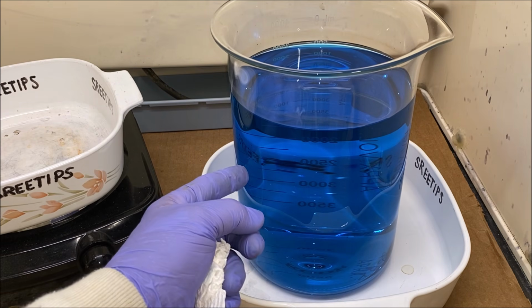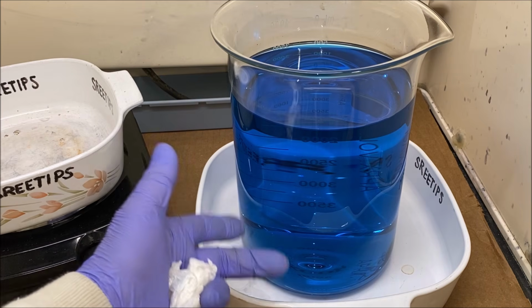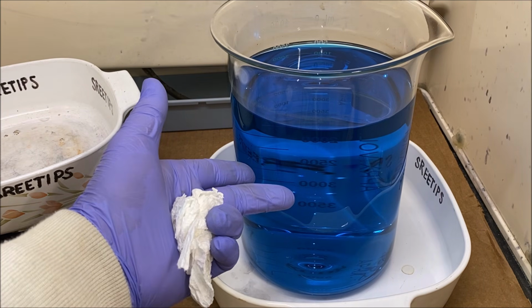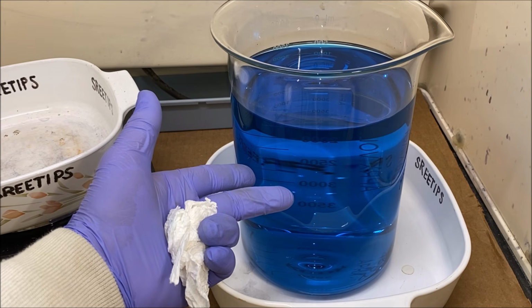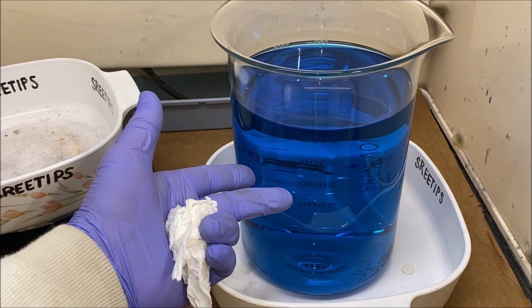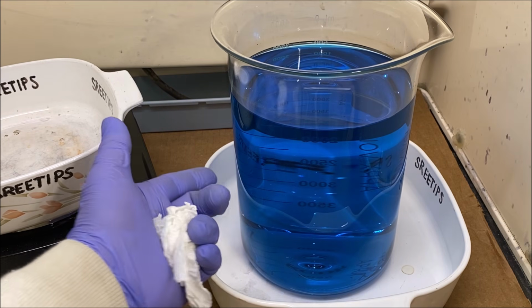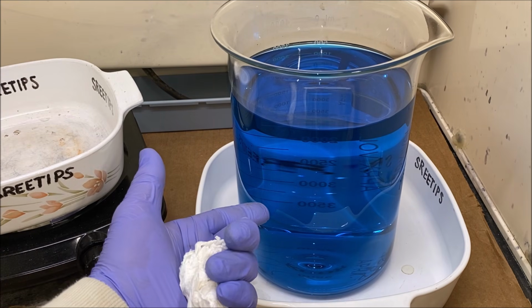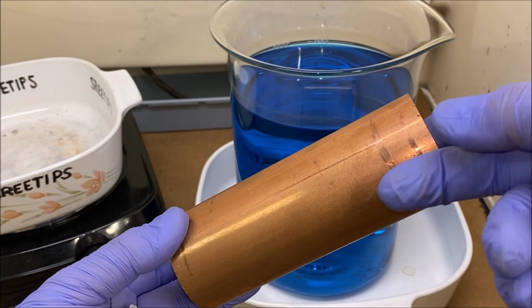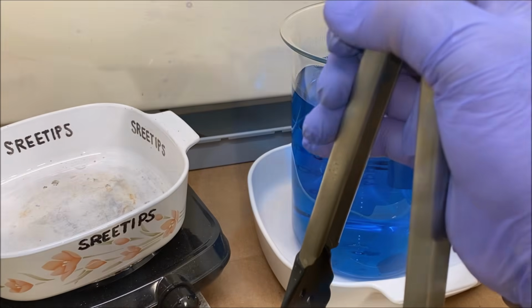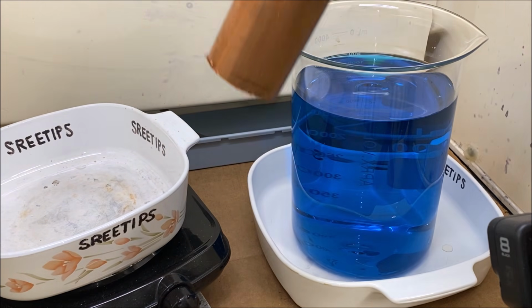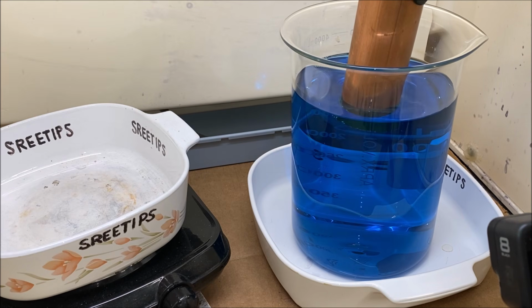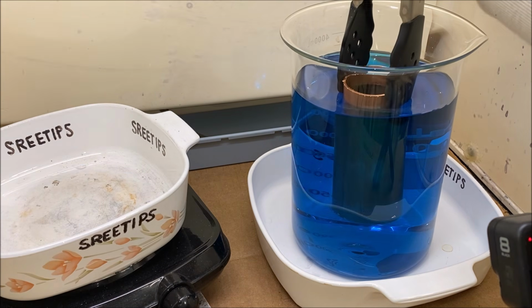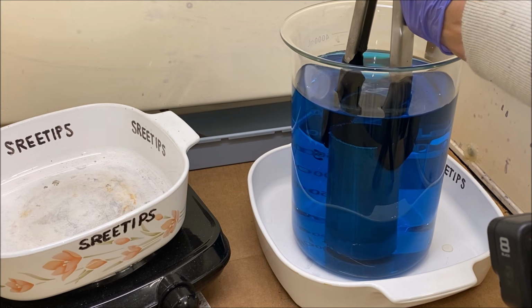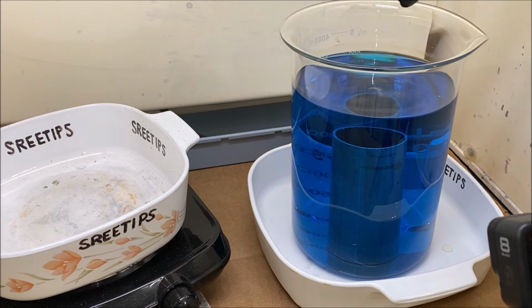But over time, the copper builds up in here, and if we use it over and over, what will happen is the copper concentration will rise, and then we could begin to deposit copper with the pure silver crystal. So this is the second use of this electrolyte. There's still silver in here, so what I'll do is I'm going to put a piece of copper in here. There's still silver in this solution, and it should cement out rather quickly on this piece of copper, and we can recover the remaining silver by adding copper to our solution.